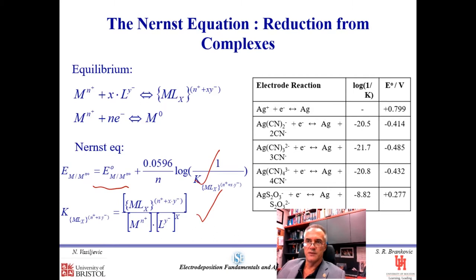This type of trick is exercised when we want to do electrodeposition of alloys where we have very dissimilar metals. For example, we want to bring them closer to each other in terms of their reversible potential, so we can avoid some transport limitations during the alloy deposition. Then we can use complexation, and the more noble metal can actually be brought closer to the less noble metal in terms of their reversible potentials.